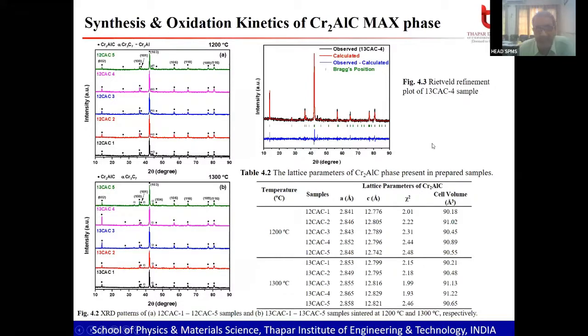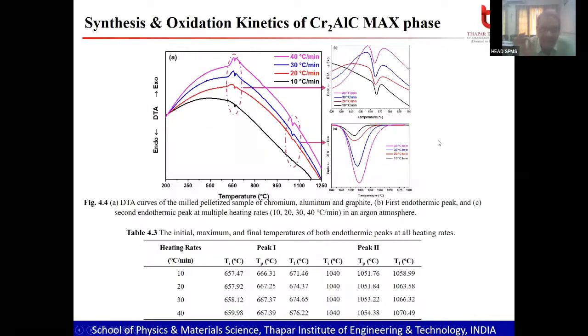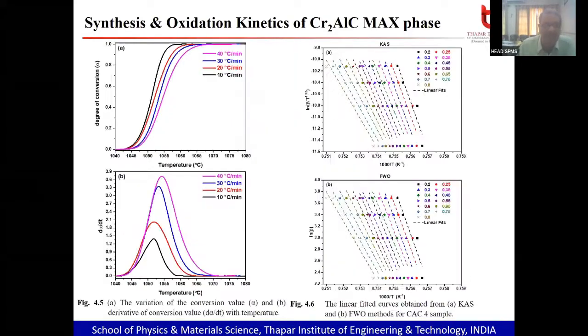Now, next important is that the kinetics of the formation of the MAX phase becomes very, very important here. By making use of thermal analysis, by heating at different heating rates, we could perform some experiments where we could predict the model, that is, what type of reaction parameters are going to take place.